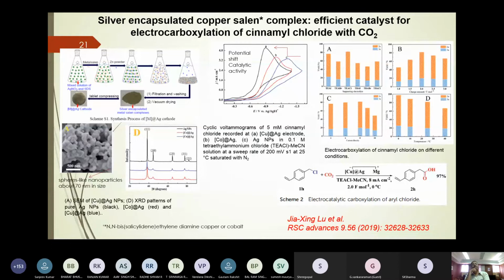Here they also use a cobalt complex, which also confirms the presence of cobalt. Cyclic voltammetry shows how the catalytic activity gets improved, for example, for bare silver nanoparticles compared to silver nanoparticles on the copper salen complex plus the cobalt salen complex. The copper salen complex with silver electrodes shows a lower potential compared to others. This shows that it acts as a good catalyst. Second, we show the yield of cinnamyl chloride under different conditions, with a higher yield on the copper salen complex incorporated silver.